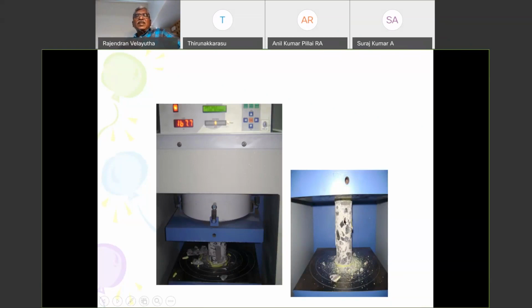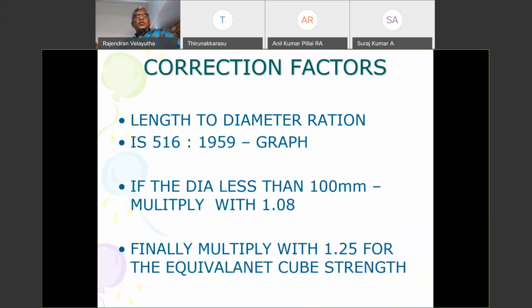Otherwise, the failure pattern of the core will not be what we anticipate, because it is not a question of only getting a number. 167.67 kilonewton has been loaded, but that is not only a number to define the expected fck value. We also need to know how the failure pattern has taken place in the core, which gives us a lot of data. Of course, we all know that you have a correction factor: if the core diameter is less than 100 millimeter, then you have to apply 1.08. But practically at site, we never use 100 millimeter because the spacing of the rebars is so close, so we always opt for 69 millimeter or 76 millimeter, where we always use 1.08, and then 1.25 to get the equivalent cube strength.